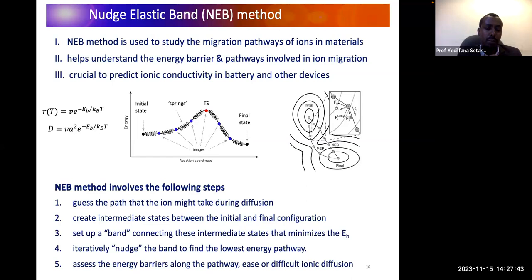Okay, so the setup has a band that connects these intermediates. This band is actually an elastic band, just like a spring, so that the positions of these ions are held at those points and the energy minimization takes place. As I have told you already, the initial and the final states are optimized, so the intermediates will be optimized, or the energy will be minimized, during the NEB calculation. Iteratively it runs and finally it gives you the NEB path, the trajectory going from initial to final with the barrier energy. So from the barrier, as I told you, you can easily calculate the rate and the diffusion constant.